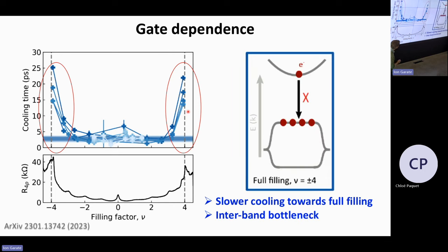This is this picture where you have this full filling of the flat band. So the picture is that you get slower cooling because you have some kind of bottleneck, because of the Pauli exclusion principle, you cannot put more electrons there. So the electrons stay at the parabolic conduction band. So this gives you then an interband cooling bottleneck in the case of full filling.